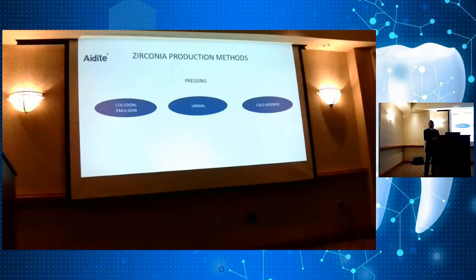So uniaxial pressing, the problem with this is that you have two very hard sides, the upper side and the lower side at 125 MPa. And this is, in my opinion, not a very good way to make zirconia, although it's relatively inexpensive. And I used to notice with my milling machines that after 25 to 30 mills, I would see sparks flying off the tools. Which means that it's actually grinding a very hard surface. When it gets to the inside of the disc, then it becomes more user-friendly. But herein lies the problem. If you're dipping that in any kind of solution to color it, you're going to get somewhat uneven density or absorption. Any questions on that?